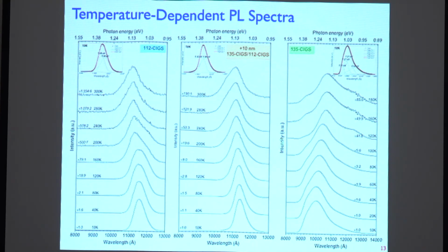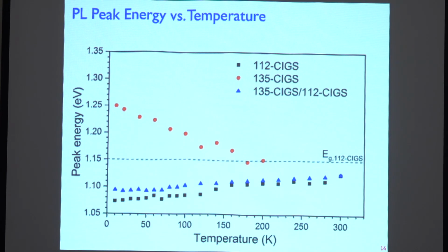We saw the blue shift; the horizontal axis is wavelength. For the 135 only, we saw the red shift instead. So this is the nature of N-type. The other is the nature of a P-type semiconductor. And when we consider the peak energy of these materials, the 112 and 112 with a capping layer of 135 show an increase in the peak energy when we increase the temperature. On the other hand, for 135, the peak energy decreases when we increase the temperature.